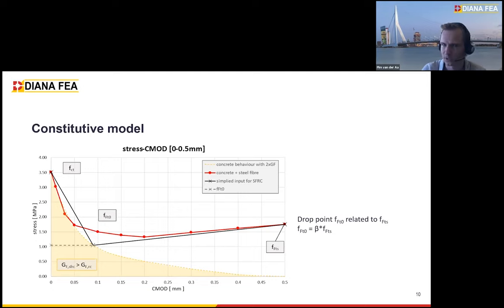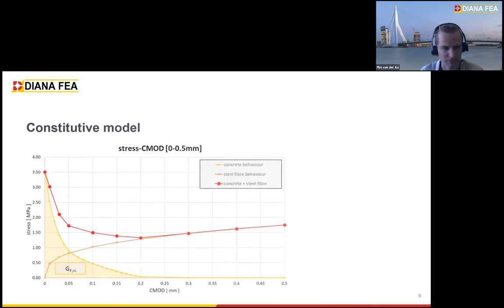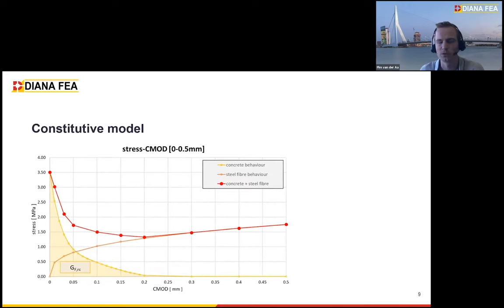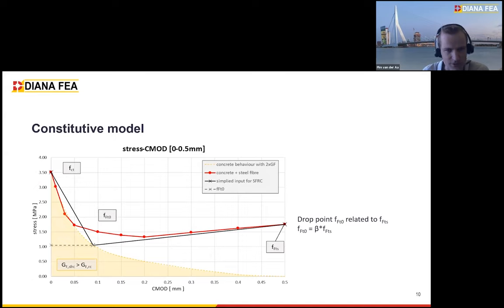Also, one other thing I would like to mention is that if we look at the fracture energy of just plain concrete, which is highlighted here with the yellow area, you can see that it is actually increasing slightly if we also apply steel fibers to it. That means the first softening branch is also increased. So that's why it is mentioned that the initial fracture energy of the first softening branch is in general a bit bigger than the softening branch of plain concrete. That's just one thing to keep in mind.